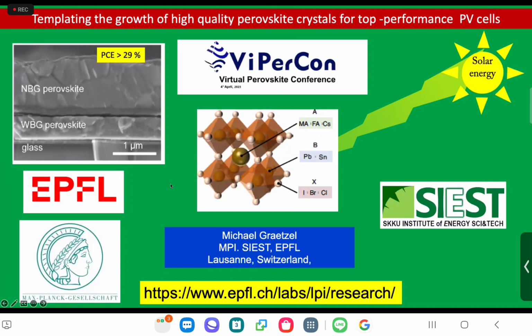And so we have collaborated with Professor Tan from Nanjing University on the wide bandgap perovskites, which is an issue. I mean, in tandems you need a high voltage wide bandgap material, which has a bandgap around 1.7, 1.8. And so there's some progress there which I want to report on. It's still unpublished.